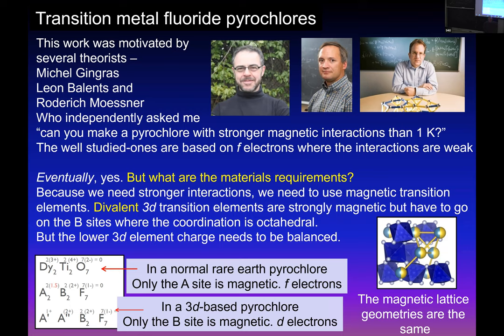That is a peculiar mineral. If you're a mineralogist, maybe you don't care about that. You just care that if I heat it up, I get chlorine out of it. But in materials physics, it's a famous structure type because you make it with rare earths. Rare earths, at the bottom of the periodic table, can have 1, 2, 3, up to 13 unpaired electrons, and depending on where those electrons are in the f orbitals, they make different kinds of magnetism. So the rare earth pyrochlores are really important. They're made with rare earths which have a 3+ oxidation state.